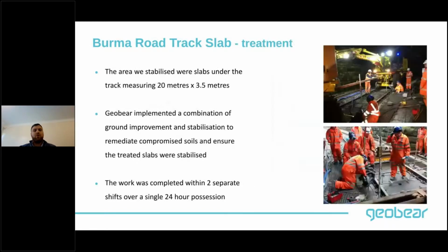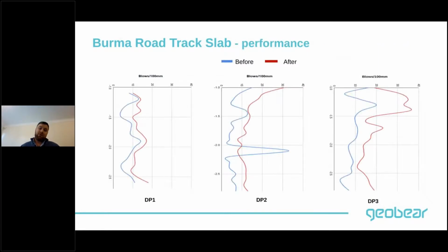So we were called into site and we carried out the stabilisation, where we actually injected into the granular material under the ground, to strengthen it but also to lift the track to the desired position. We completed the work within 2 separate shifts over a single 24-hour possession. And we also carried out dynamic probing before and after the stabilisation work.